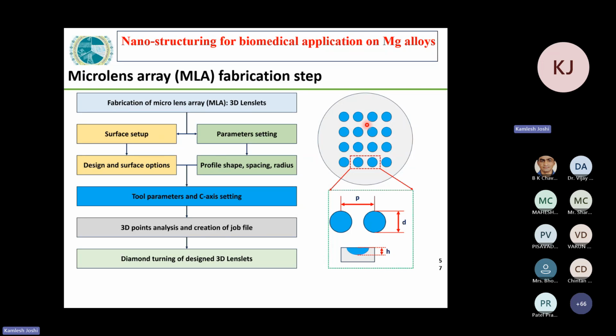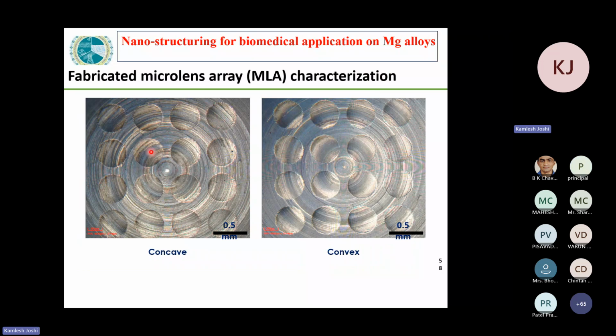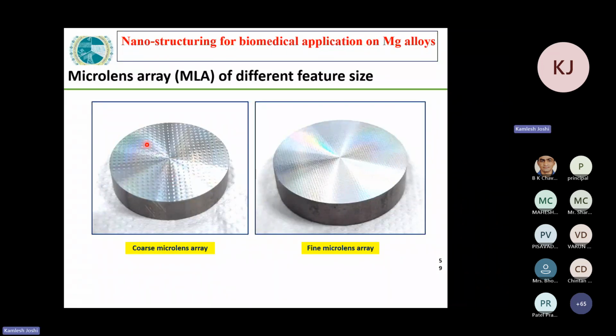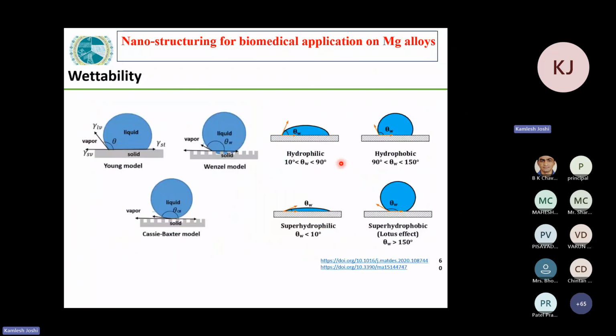We created the convex lens as well as the concave lens. We used dry machining conditions as well as lubrication conditions, and we varied the pitch between the two lenses as well as the diameter of the lenses, and this h is the depth at which the lenses are created. These are the optical images of the machined surface. You can see the concave lenses shown here as the micro lens arrays, and here we can see the convex type of lenses over this part. These are the coarse micro lens arrays produced on the surface of the magnesium alloy, and the fine micro lens arrays produced on the surface of the magnesium alloy.